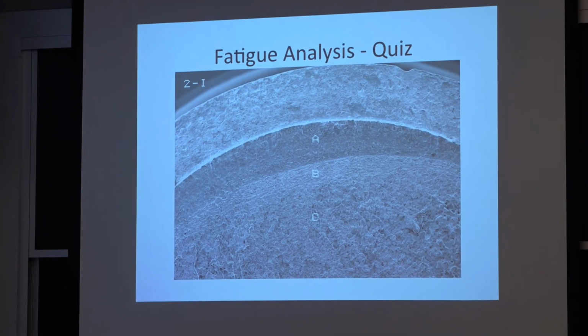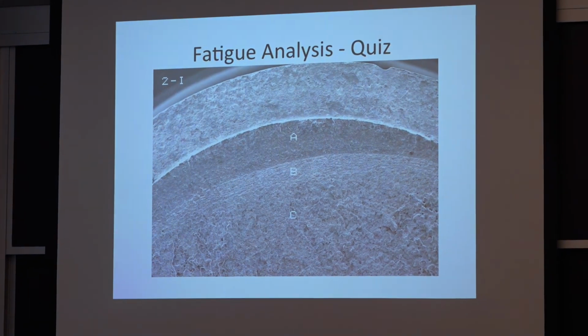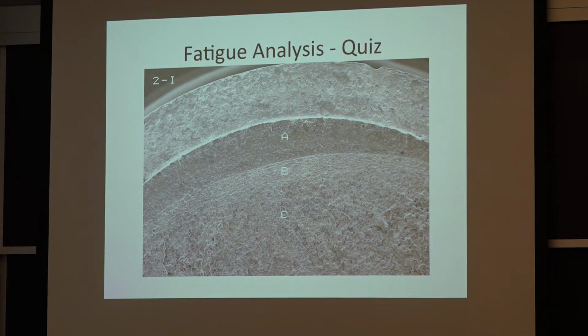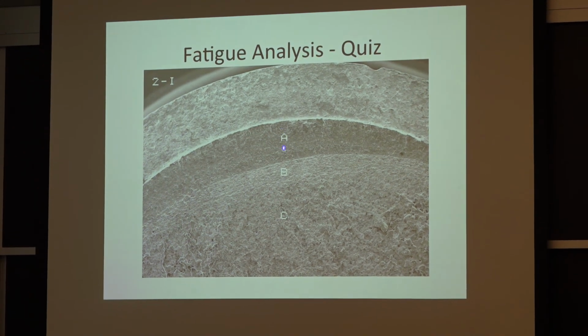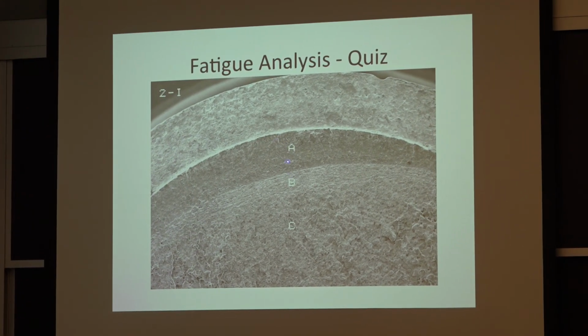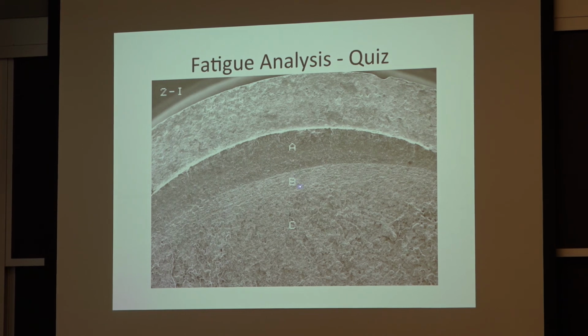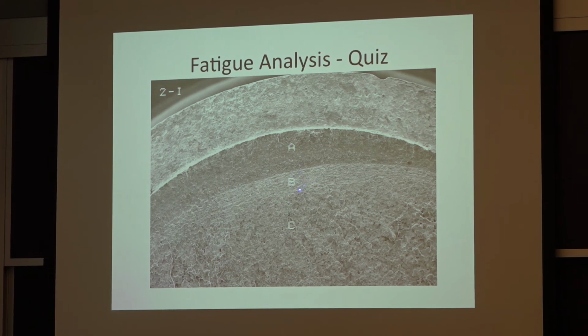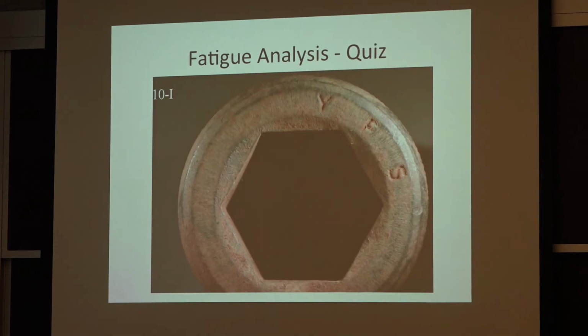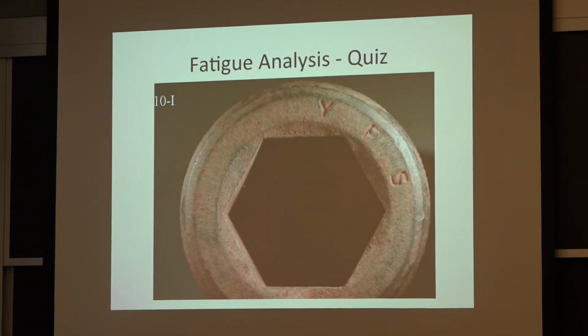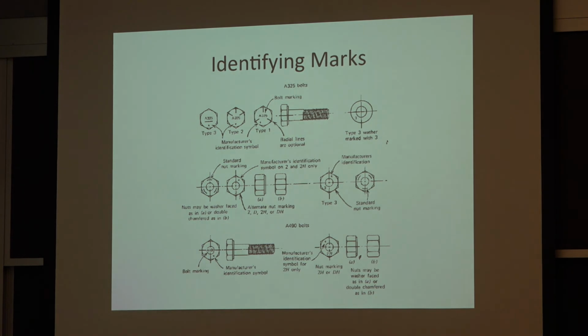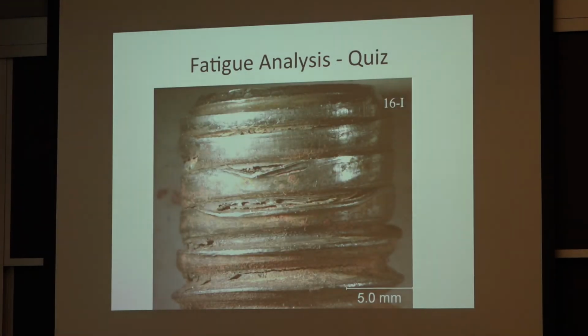This one was on a turntable, and you can see the fatigue crack A, B, and C. Low cycle fatigue, high cycle fatigue, low cycle fatigue, final fracture has a different appearance to the fracture. And then I actually had a quiz for the students after some things. This is one where obviously the nut wasn't tight. It was peening itself apart.